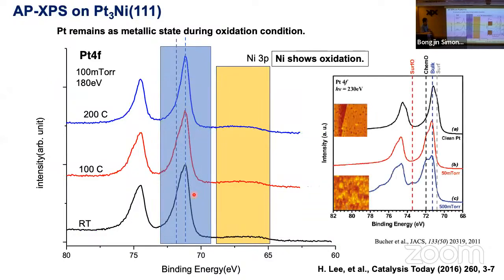I'm sorry, this was previously platinum 110. This is the platinum 110 STM image that we saw at the time. This was our measurement. At the time, we saw similar nano clustering on the STM on the surface. And when we introduce oxygen, we start to see this platinum showing these oxide features. But in platinum-3 nickel, we didn't see any of those.